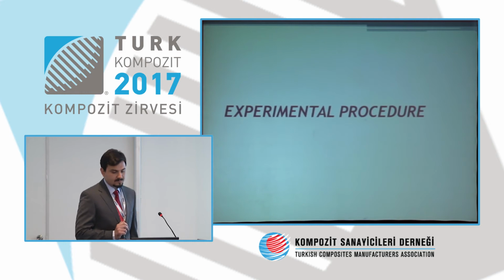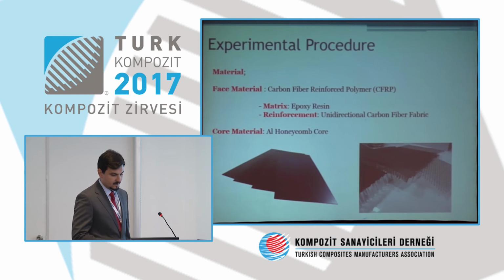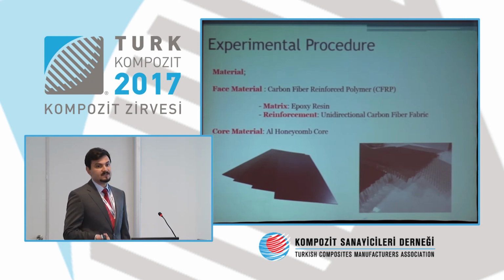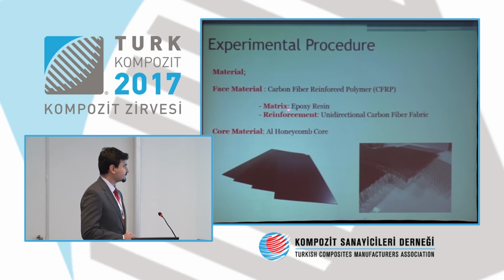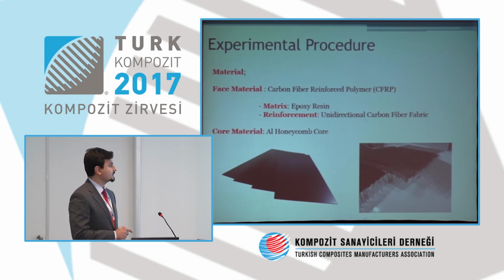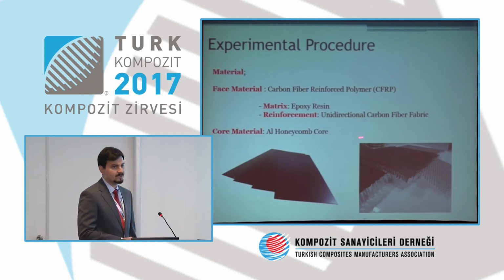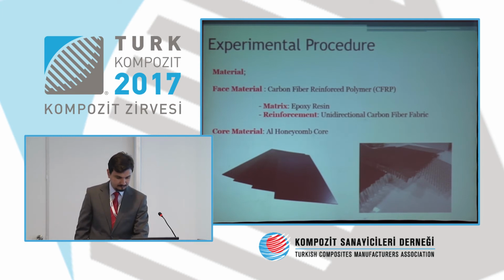Then I will pass to our experimental procedure. First of all, the materials that we use. Carbon fiber reinforced polymer we used as the face material with the orientation of 0-90 and 4 layers. Our matrix is epoxy resin, and reinforcement is unidirectional carbon fiber fabric. And we use aluminum honeycomb core, as you see here, as a core material.